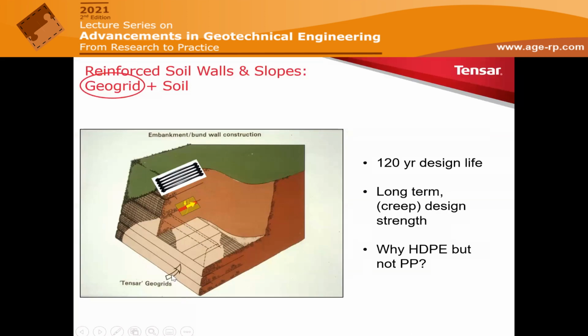We can design for up to 120 years design life. And I hope everybody knows that we design for long-term or creep design strength, because geogrids or polymer is viscoelastic. So we know it's going to creep, but we know exactly by how much, and we extrapolate, and we know exactly the strength, or residual strength, we should be designing them for. And this is exactly why we make them, when it comes to polymer, with high density polyethylene and not polypropylene.